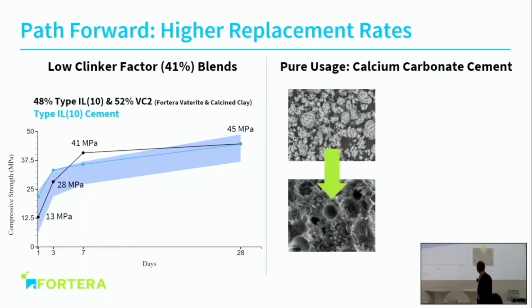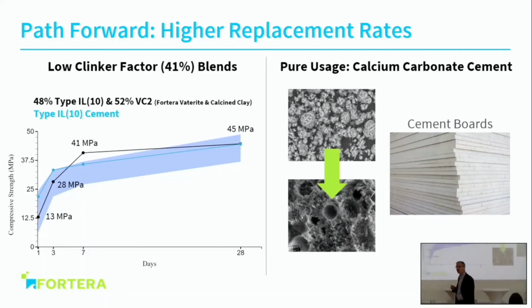And on the right, you see another usage of our reactive calcium carbonate, when you use it as a pure binder. The transformation of vaterite into aragonite will bring a different concrete that can be used for some usages, such as fiber cement boards. If you're interested, we have some samples of fiber cement boards on the table for people present here. We believe this is a very promising technology. This is a way to have the best out of our technology, because when you use it 100%, you have the full benefit of the CO2 reduction.